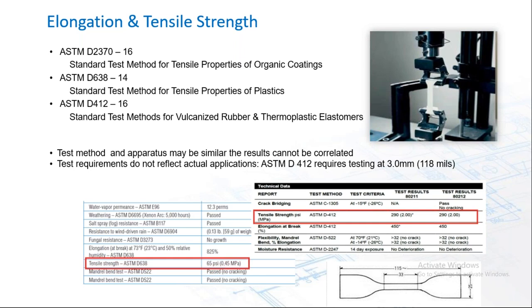It's strange though that SWRI, Sealant Waterproofing Restoration Institute, should actually fall in behind ASTM D412, because strictly speaking, that test requirement is a film thickness of 118 mils, about 10 times the normal thickness of a facade coating or a waterproof coating. And herein lies some of the problems, because now the manufacturer or the test criteria has been modified to application thicknesses, where it does actually reflect a real life application, but you're not to know that until you know it.